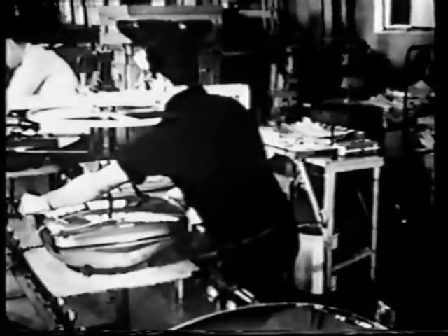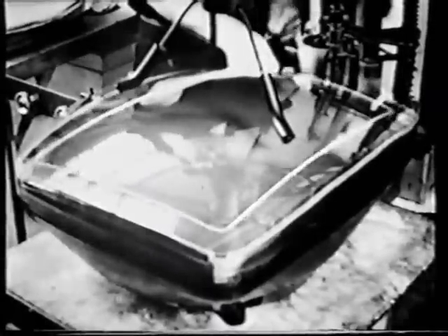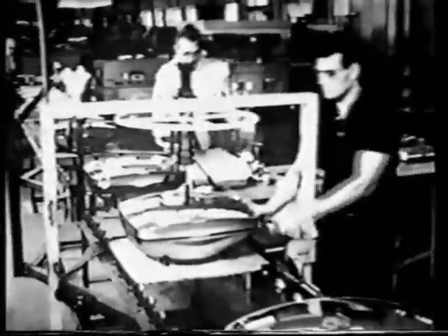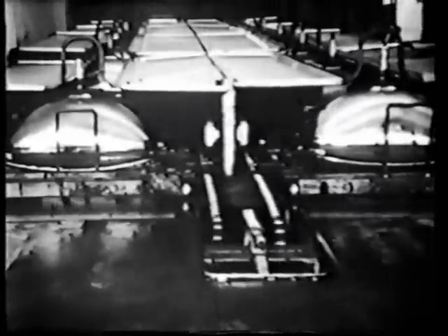Several methods of providing protection of picture tubes against external damage are used these days. This particular one employs the use of a glass safety screen that is bonded to the picture tube. Having been cleaned and polished, the protective screen is fitted to the tube, leaving an airspace. After passing through a preheating oven, the airspace is filled with a transparent bonding resin, and following a further heat treatment process, the completed tube is ready for final test.